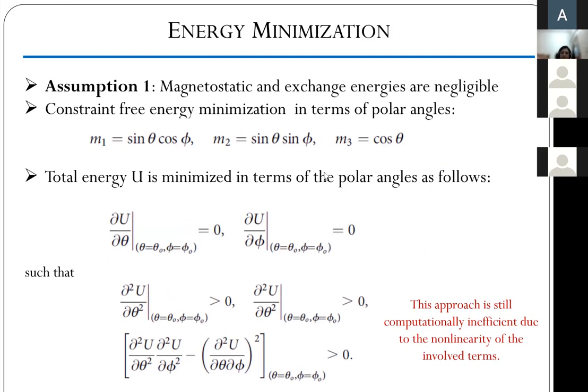So when we minimize the energy, we take m1 equal to sin theta cos phi, m2 equal to sin theta sin phi, m3 equal to cos theta. We go ahead and minimize it such that at theta equal to theta naught and phi equal to phi naught, del u by del theta is 0, del u by del phi is 0. And then to ensure that the result is a minimum, we additionally have to impose these constraints, right? These equations are fairly straightforward, and by taking polar angles,